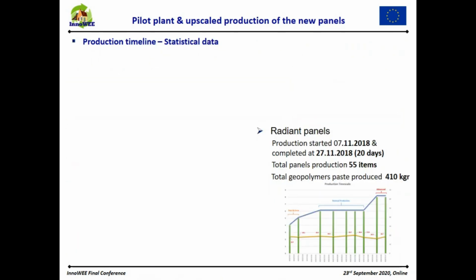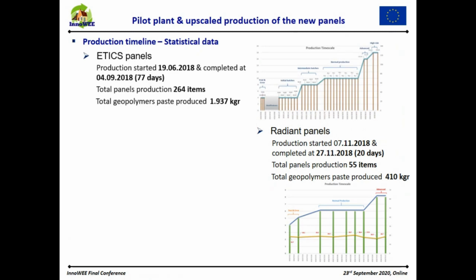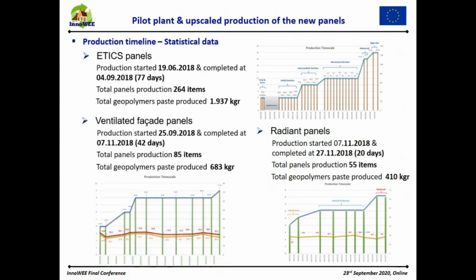And here is some statistical data. As you can see, for the radiant panels, the production lasted 20 days and 55 items were produced, and the geopolymeric paste was around 400 kilograms for the radiant panels. For the ETICS, the production lasted 77 days, 264 items were produced and almost 2 tons of geopolymeric paste. And finally, for the ventilated facade panels, the production lasted 42 days, 85 items produced, almost 700 kilograms of paste.